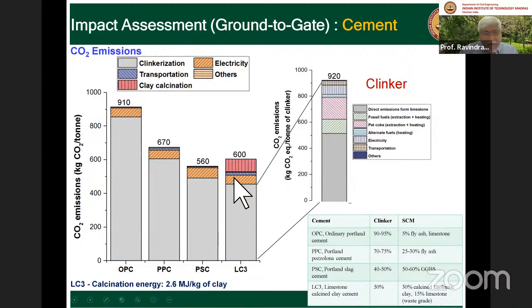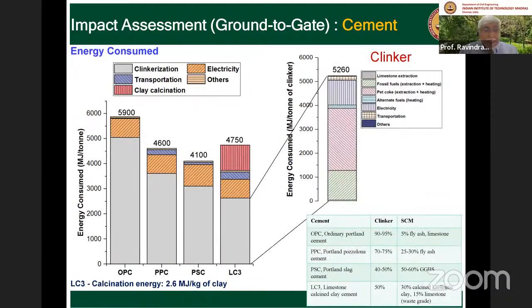There is some part from the clay calcination. There have been questions if that is very significant. And you see it is much less than what is coming from the clinker. It is there, but it is much less than coming from the clinker. And here I have assumed that the OPC has 90 to 95% clinker, PPC has 70 to 75% clinker, PSC 40 to 50%, and the LC3 has 50% clinker. So you clearly see how much there is a reduction in the CO2 emissions when we are comparing LC3 with OPC. Now let's look at energy.